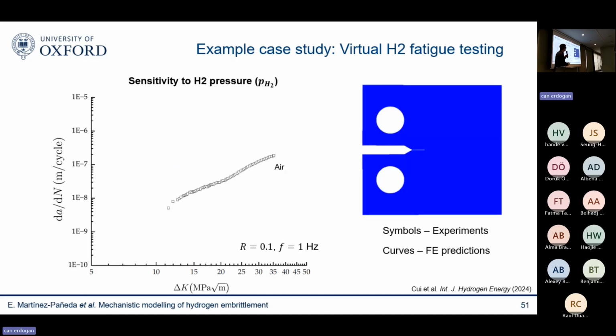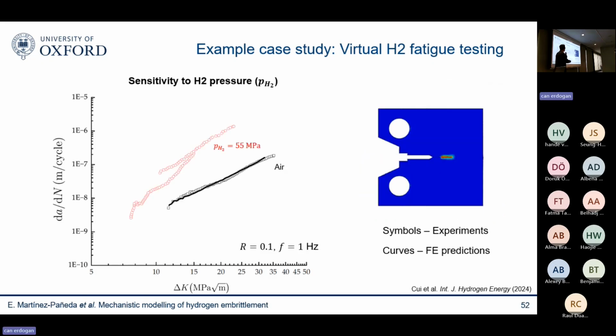So we run our virtual experiment. This is my compact tension virtual experiment. I see my crack growth. And of course, I get an excellent agreement with experiments because I'm fitting those 2 parameters. There's no hydrogen here. I'm just fitting those 2 parameters. Okay, so now there's no more fitting. Now we have some hydrogen data at 55 megapascals.